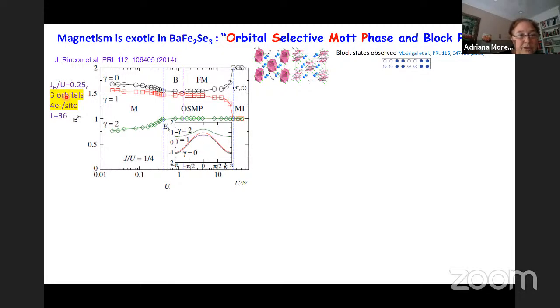Notice that the dispersion we chose, in 1D, is such that 2 of the orbitals form hole pockets at the center of the Brillouin zone, and the 3rd orbital produces electron pockets at the boundary of the Brillouin zone, to capture the behavior observed in the higher dimension pnictides. We studied the population of each orbital, and these orbitals are not hybridized—each one is an independent orbital.